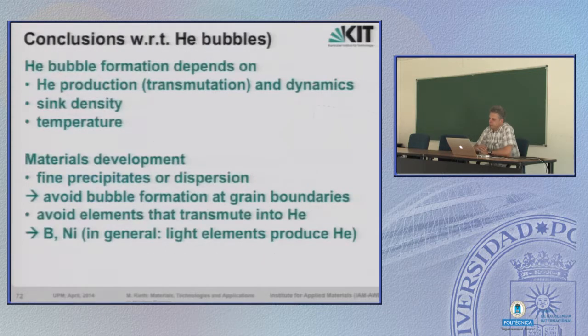Conclusion with respect to helium bubbles. Finally, the helium bubble formation, of course, depends on the transmutation rate and dynamics, also on the sink density. If the bubbles are distributed finely along many dislocations or precipitates, then it's less dangerous. This is also where ODS steels came into play. Temperature makes also a difference. At lower temperature, helium bubble formation is not such a problem as it is at higher temperatures.